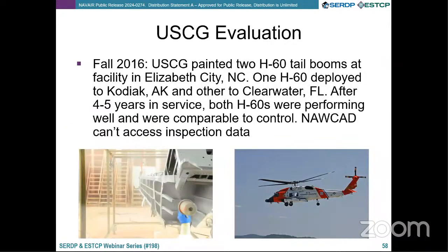Likewise, we had sent some very early aluminum-rich primer formulations from one of the manufacturers to the U.S. Coast Guard depot facility in Elizabeth City, and they painted the tail boom of 2 helicopters, put them in service for 4 to 5 years. And while we weren't able to inspect these personally, the engineers responsible for that program were happy with the performance to the point where we've initiated a much larger demonstration of the technology with the Coast Guard.